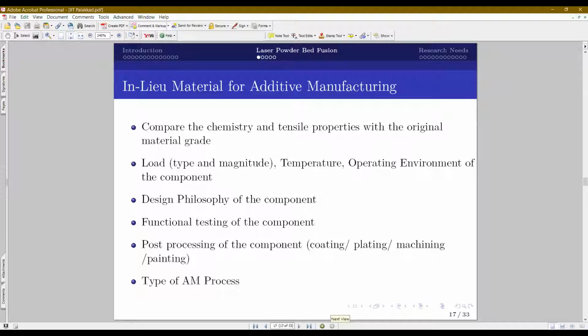So what we generally do is take a component, understand what the original grade is and what the tensile properties are, and map it with the 3D printed grades. Chemistry most of the time doesn't match, hence we only use chemistry to understand whether I am choosing a similar kind of material. Titanium means titanium, aluminum means aluminum, steel means steel. For that reason only, chemistry is needed. Whereas tensile property plays a huge role, wherein I'll try to fit the tensile property. Most of the time what we find is that if strength is high, ductility is less, or the other way around. So we try to map it and see that the variations are less than 5%. Then only we fit it; otherwise we don't fit the equivalent grade.